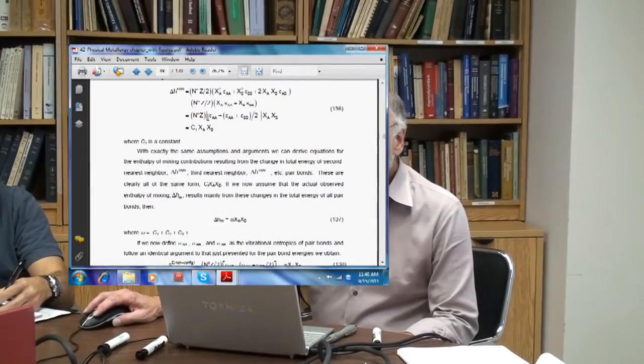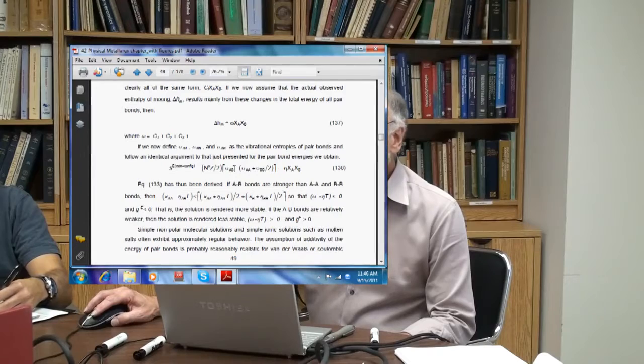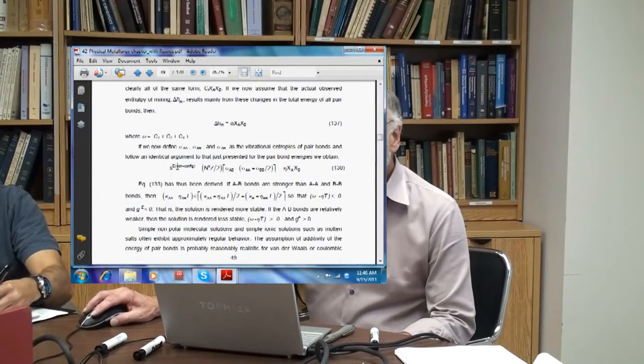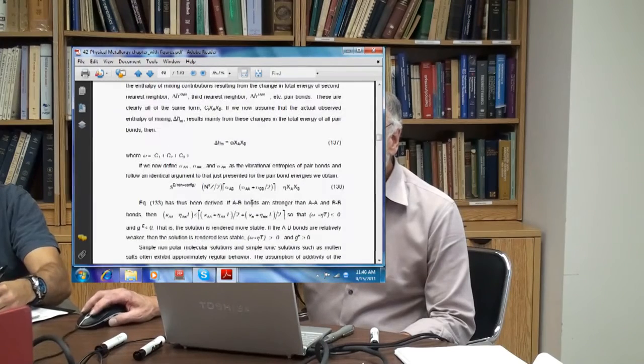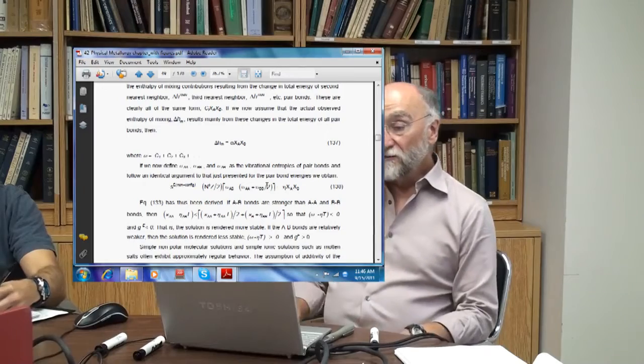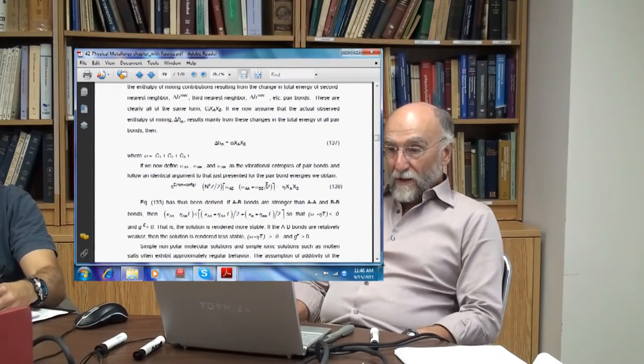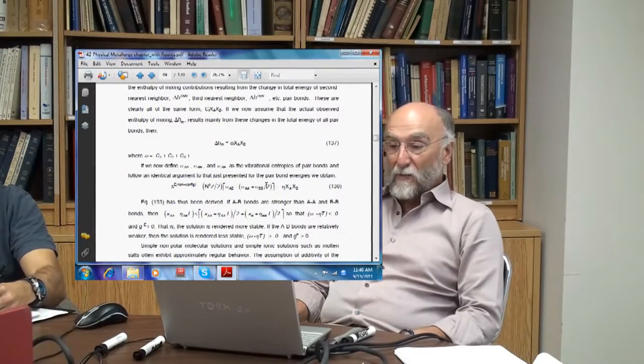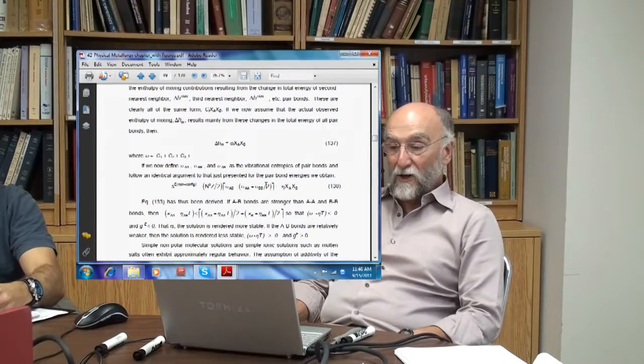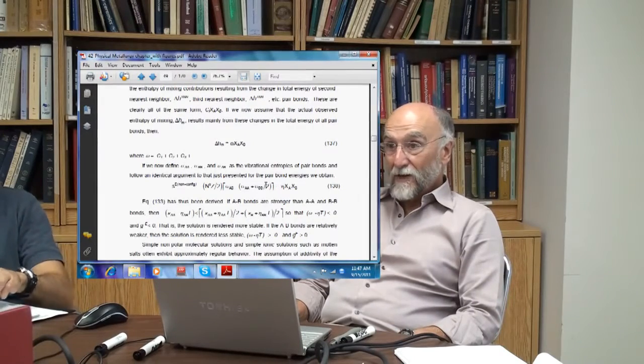Configurationally, it's still randomly mixed, but remember, there's the energy, there's the entropy. As you heat a pure material up, the entropy goes up because of the vibrational spectrum, and we're now assuming that the vibrational spectrum of the solution is not the same as the phonon spectrum of the pure materials. So now it gets a little more dicey. You can do exactly the same definition as we did before, but instead of talking about an energy of a bond, you can talk about the excess entropy of a bond as sigma AB. So your excess non-configurational entropy is exactly the same equation as here, except these are the differences in the non-configurational entropies of the bonds. I wouldn't know exactly what the non-configurational entropy of a bond is, but let's assume that it's a reasonable sounding term, and so clearly you end up with exactly the same sort of expression for the excess entropy as you do for the heat.